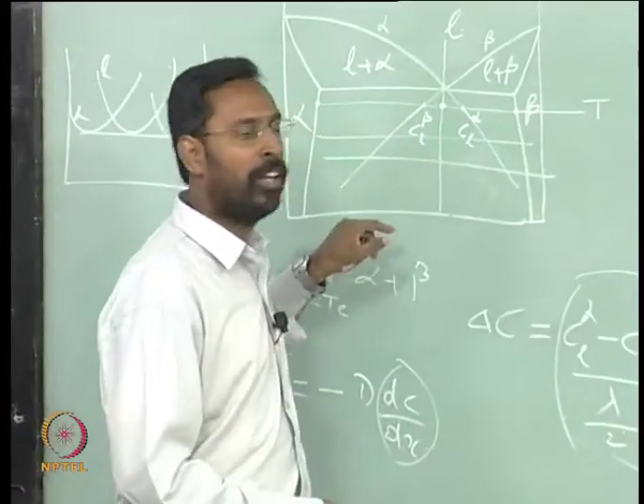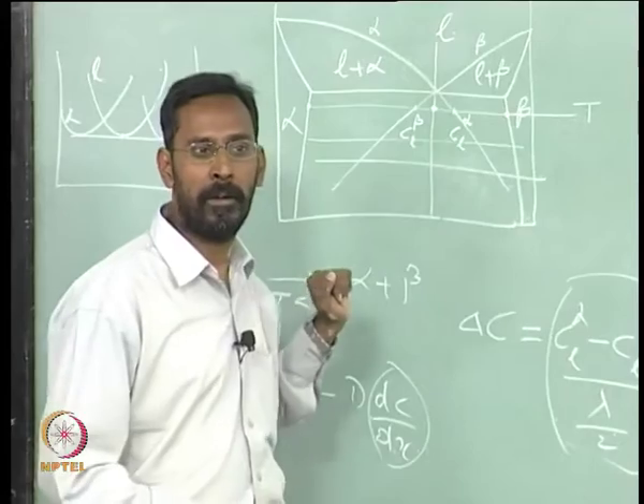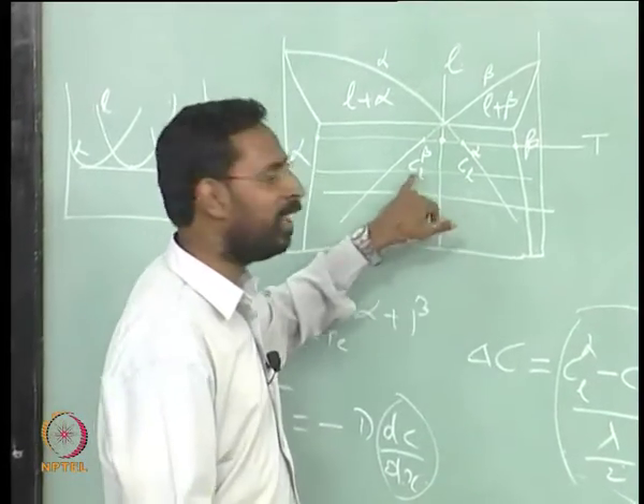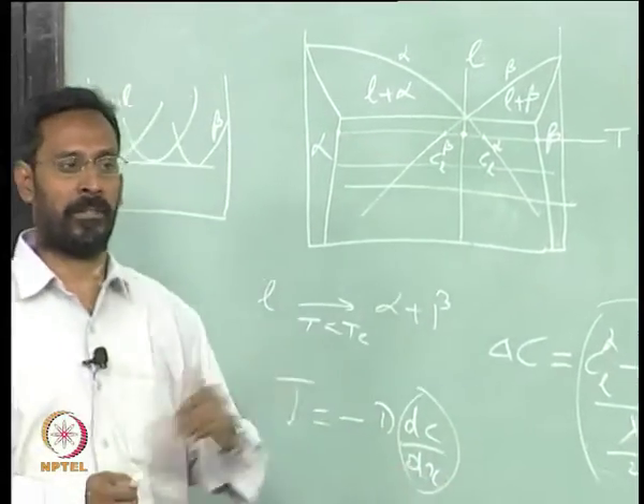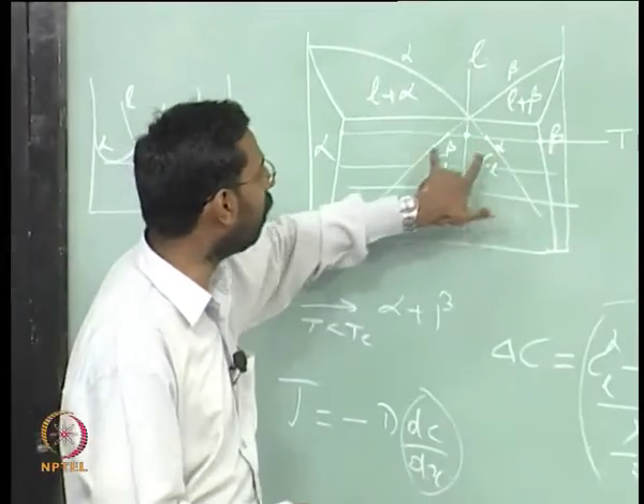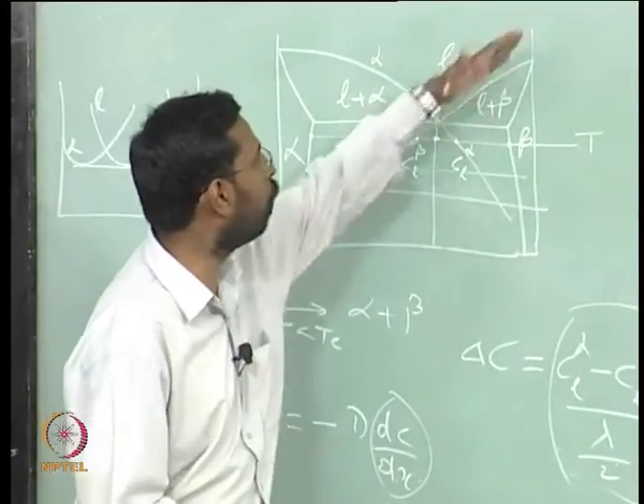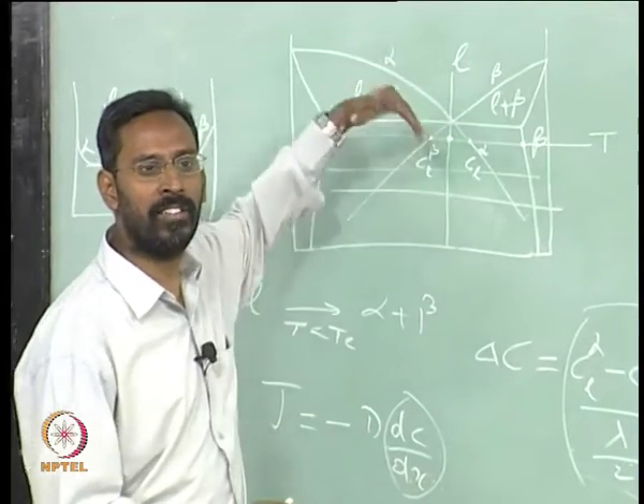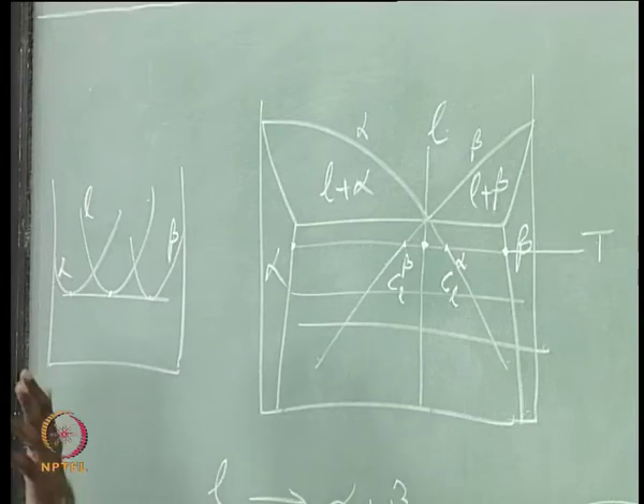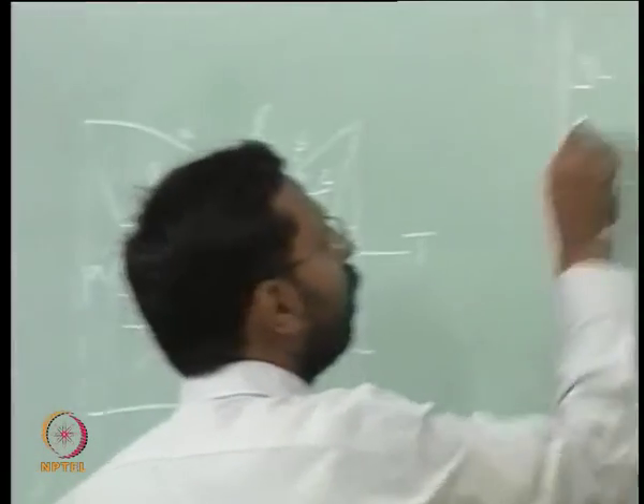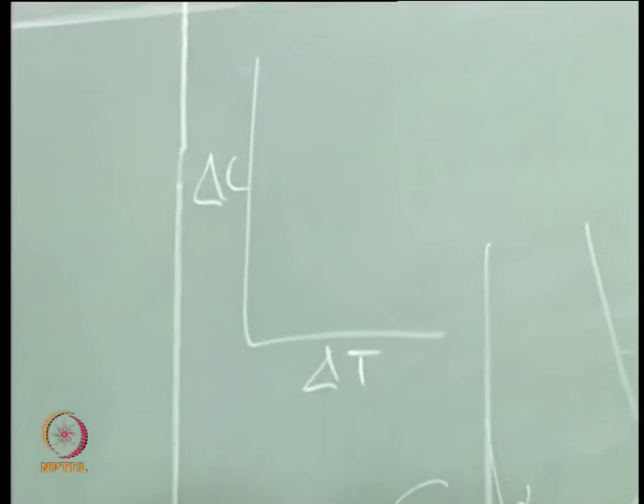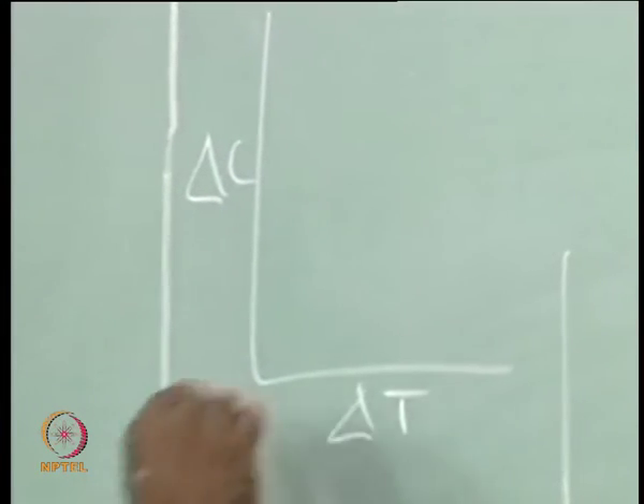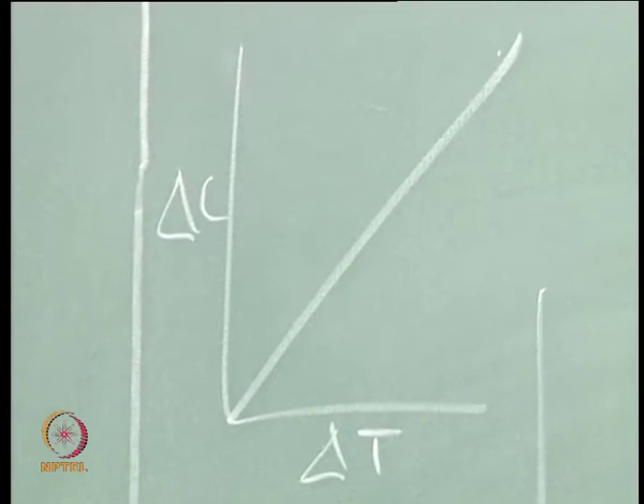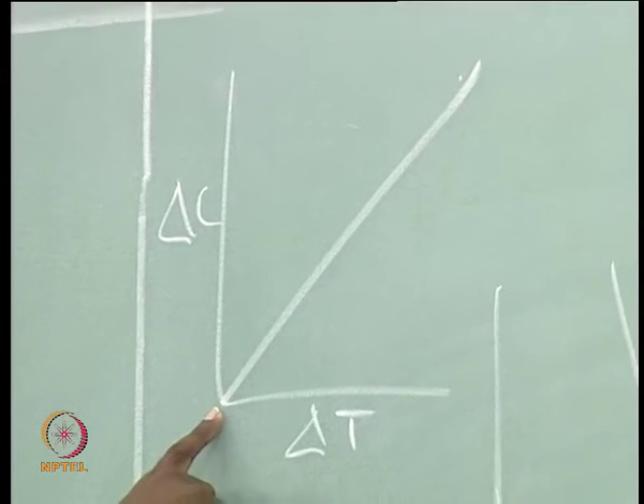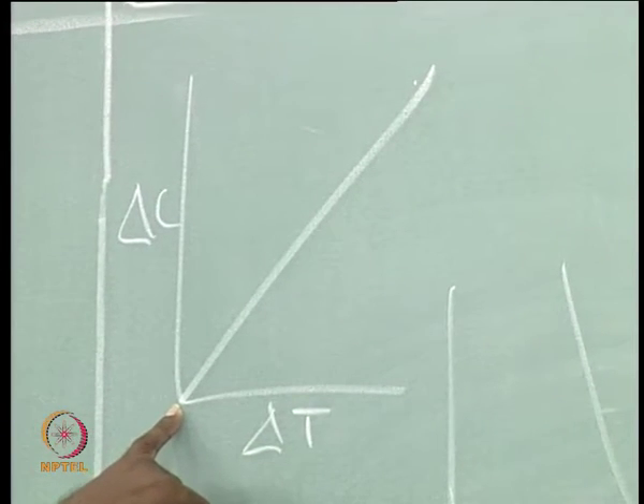If I assume that these are linear, then I can assume that the delta C is linearly dependent on the temperature, because this difference can linearly increase with temperature if these two are straight lines, not curved lines. If I assume them to be straight lines, then if I plot delta C versus delta T, where delta T is undercooling, I will see that this will be linear, and at delta T being 0, delta C has to be 0.